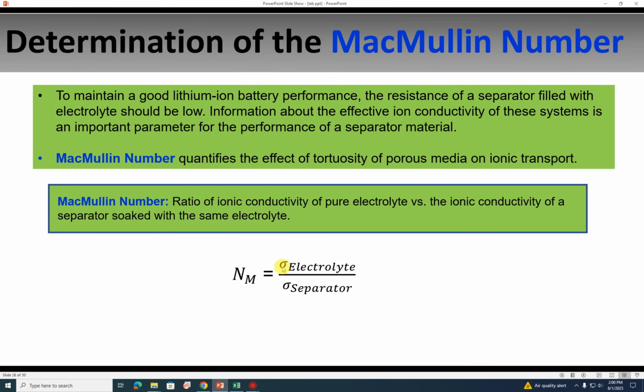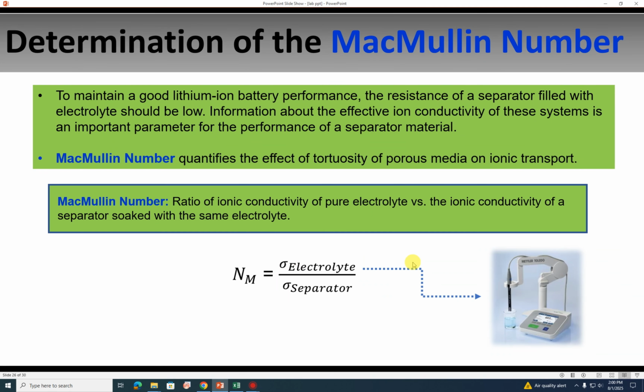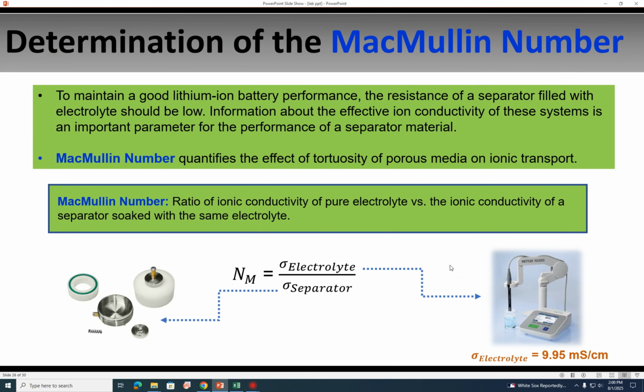So first step is to measure the ionic conductivity of the electrolyte, which we can measure using this meter inside the glove box or outside the glove box. I have measured the ionic conductivity of electrolyte, and its value is 9.95 millisiemens per centimeter for the LiPF6 in EC and DC. Now next step is to measure the ionic conductivity of separator, but unlike my previous video, today I will use another method which is more effective to measure the ionic conductivity of separator.